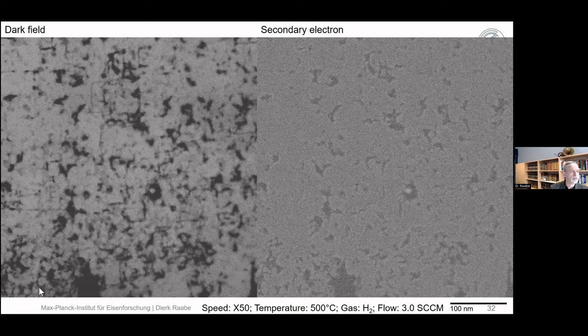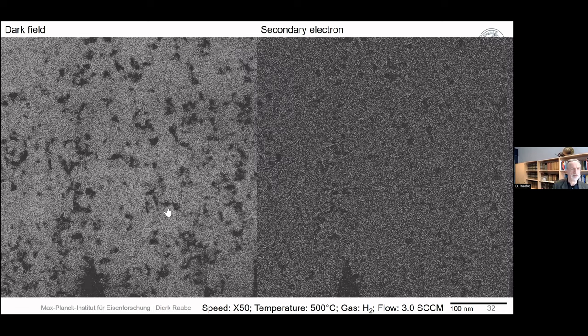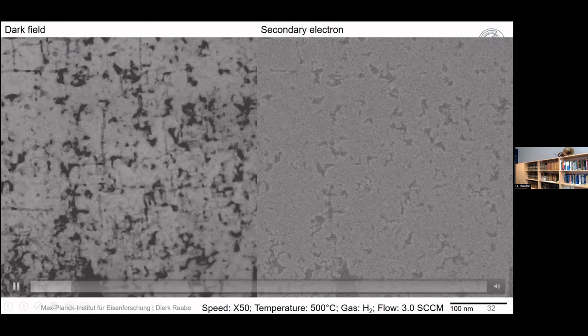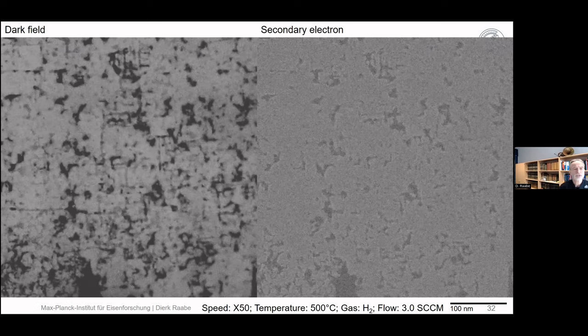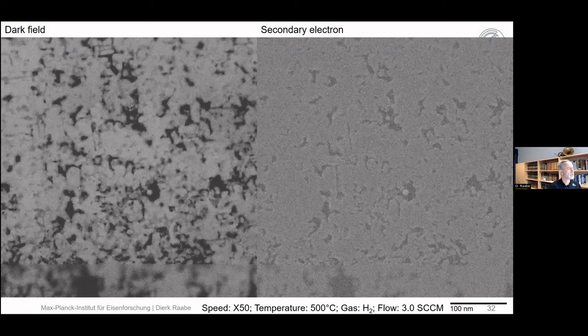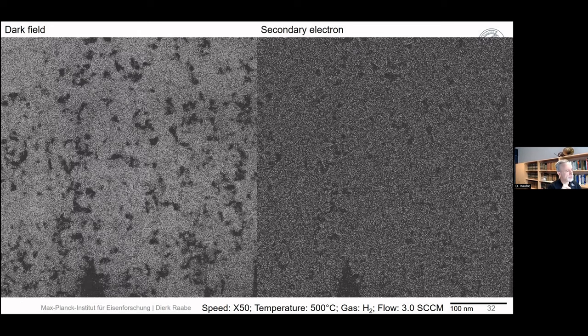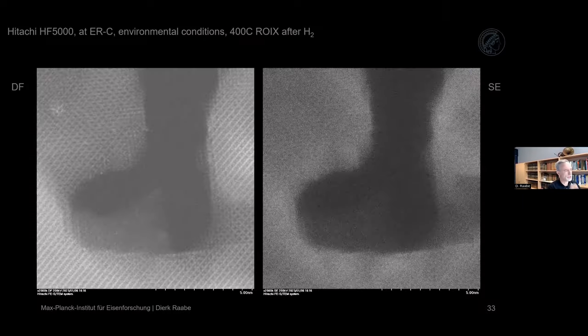Let me maybe show that again, and you can better see that. So that means you see here how the first iron nucleus is directly formed. Here we are at a low temperature of about 500 degrees centigrade. And that means we directly transform from our single crystalline magnetite, the sputtered spinel single crystal, and out of that, we go directly below the Wüstite point in the phase diagram to pure iron.